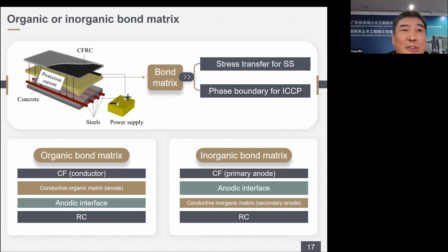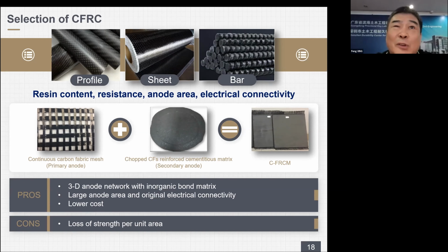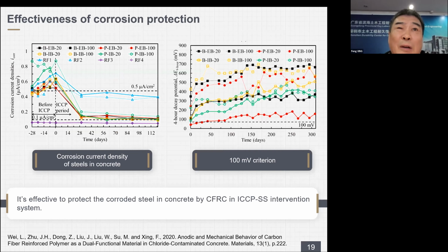On the other hand, cementitious matrix provides ions. Therefore, in this case, CF is a real primary anode, and the cementitious matrix is secondary anode. This makes the anode area even larger, and the system is even more durable. Selection of CFRC is also a key problem. After a series of research, we finally recommend continuous CF mesh and inorganic cementitious materials to form the composite anode by comprehensively considering the anode area, electrical conductivity, and material cost. Based on the above considerations, the ICCP-SS system was developed.